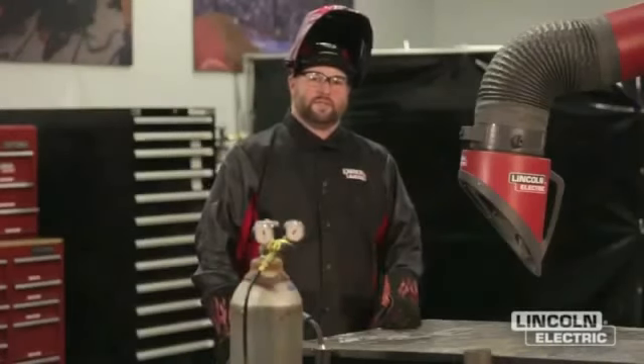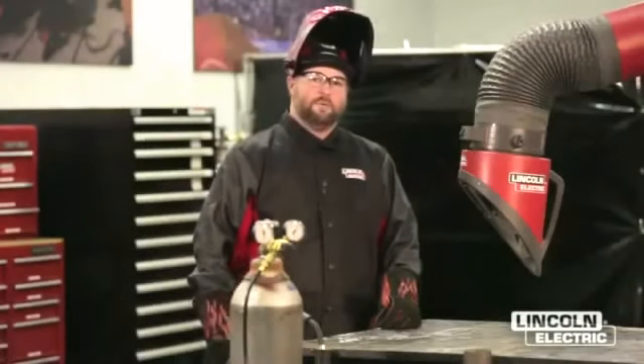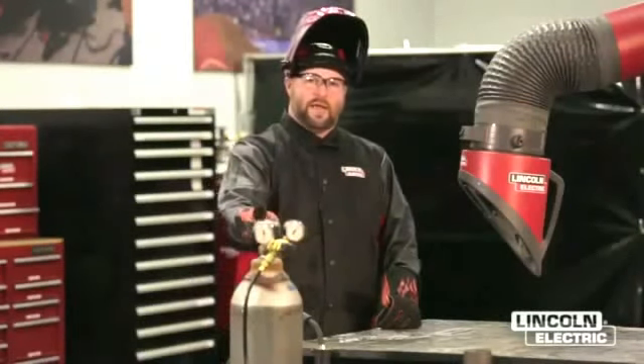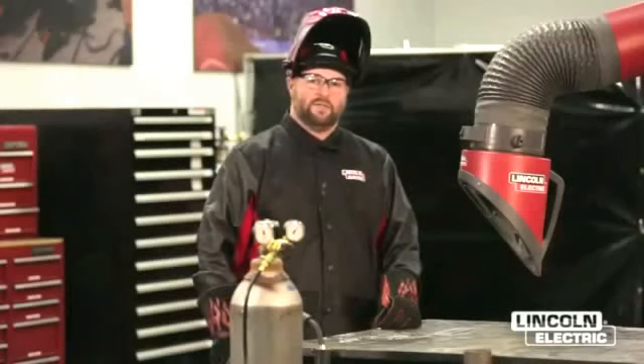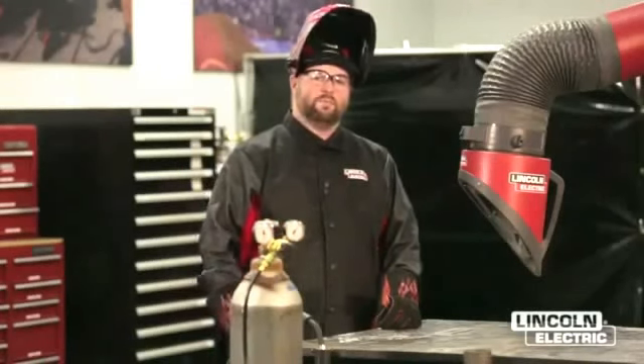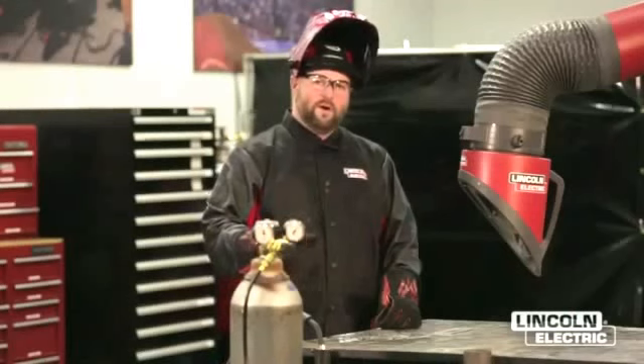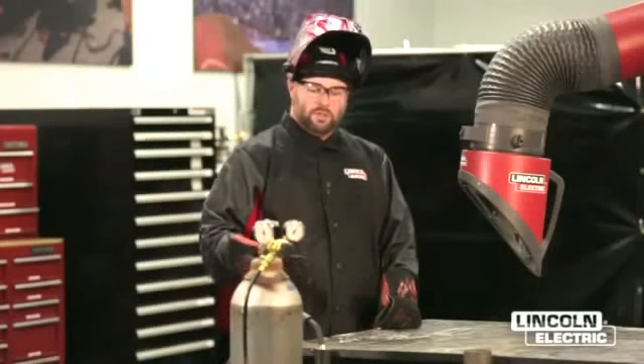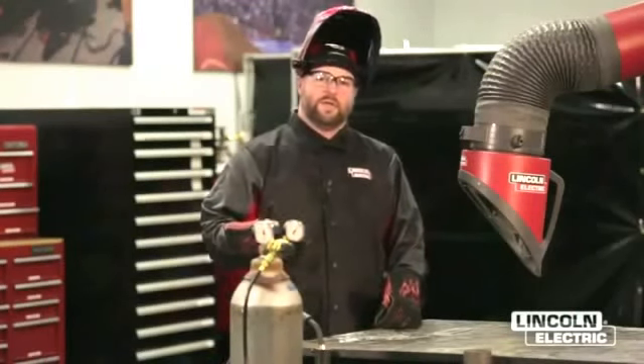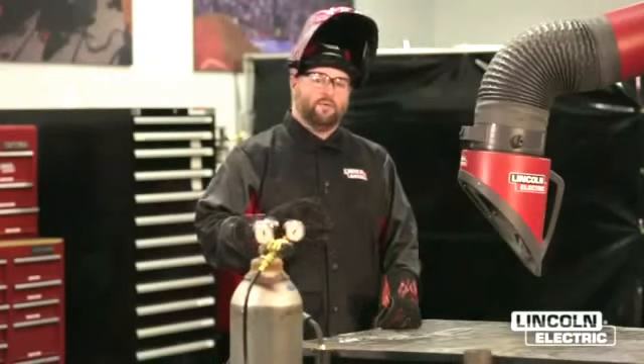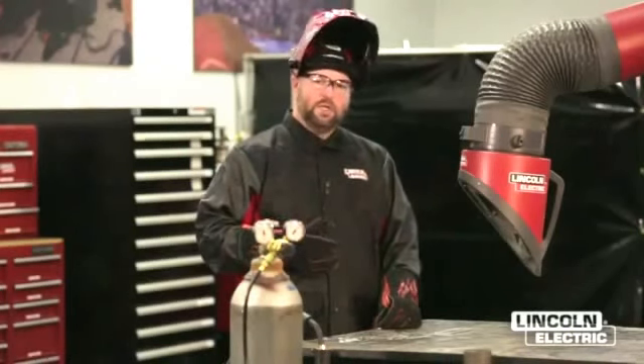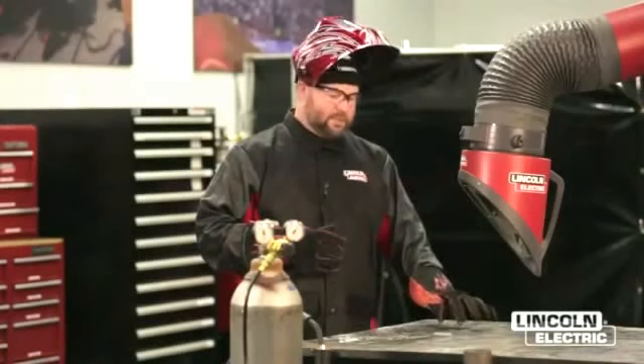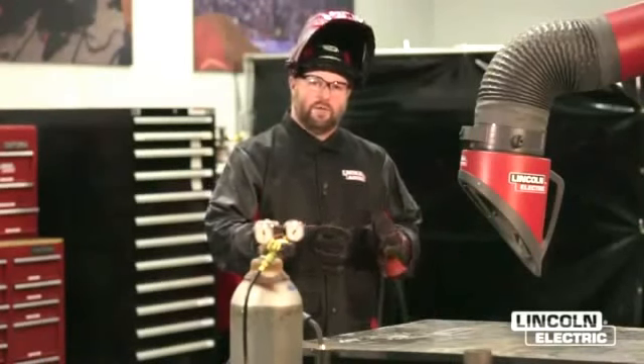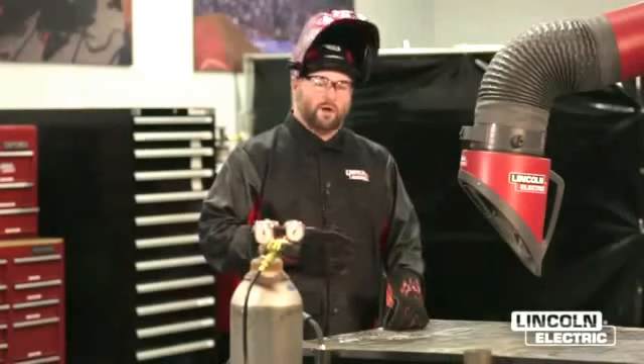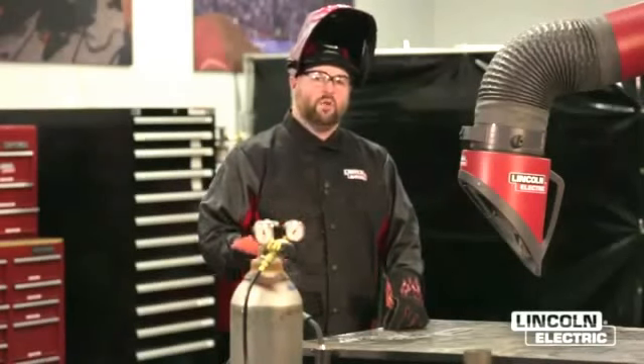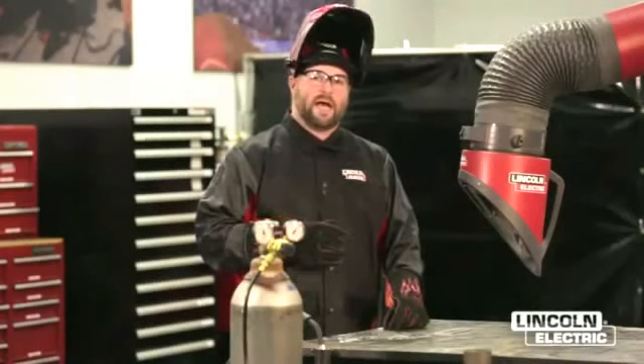Next, we're going to talk about the effects of our shielding gas. For the GMAW process, our gas mixture that we have here, our 75 argon, 25 CO2, is what's protecting that molten puddle from the atmosphere. So it's very important that we have the proper coverage for our weld. The one thing is we could have too low of a flow rate and we won't get adequate gas coverage. The other thing may be that we have contaminants on our base material and we'll start to get pinholes and porosity involved there. The other thing is we don't want to use too much gas. Too much is not better.